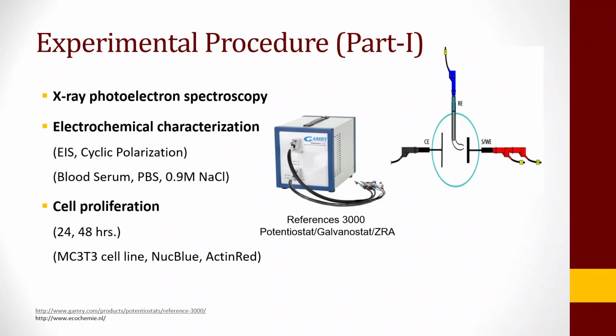By the way, we have used 3 different types of mediums or simulated fluids. The first one is a blood serum, that's a real blood serum, and then we have a simulated phosphate buffer saline and also 0.9 molar NaCl. And as far as the biocompatibility studies were concerned, we have used a pre-osteoblast MC3T3 cell line, and we have taken pictures of these cells on the top of these 2 different types of manufactured 316L stainless steel after 24 and 48 hours. And then we highlighted them, the nuclei and the cytoplasm using NUC blue and actin red.